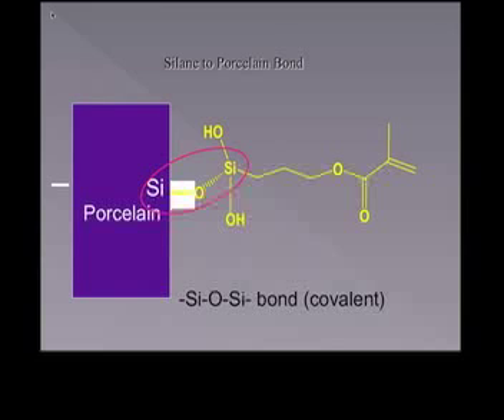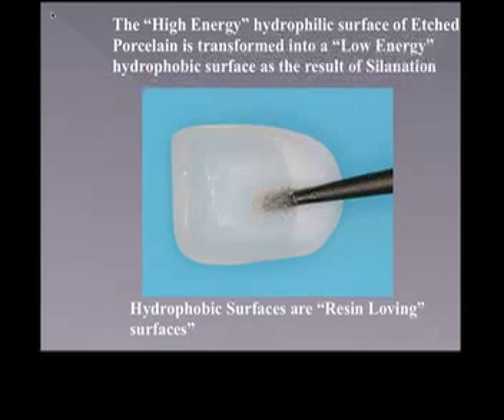Warm air, this is a tip, will drive the interaction further and lead to more efficient silanation with improved siloxane group function. In other words, if you silanate your crowns and blow a little warm air on them, it's going to make that bond stronger and improve not only the flow of resin onto the indirect substrate, but mitigate crack propagation as well.